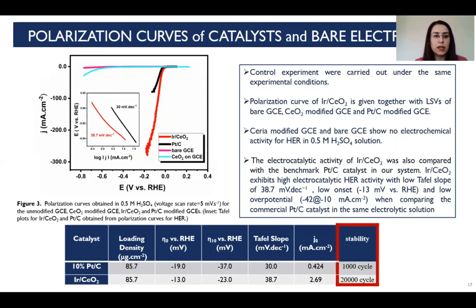Ceria modified glassy carbon electrode and bare electrode show no electrochemical activity for the hydrogen evolution reaction. On the other hand, iridium ceria exhibits good activity with low onset potential, low overpotential, low Tafel slope, and high exchange current density values when compared to the commercial platinum carbon catalyst. However, iridium ceria exhibits higher stability than that of the platinum carbon catalyst. So it is a promising electrocatalyst towards the hydrogen evolution reaction.